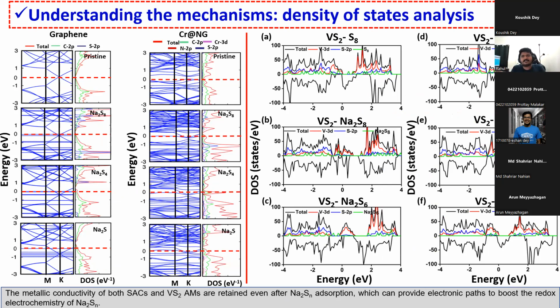Now we have done the density of states analysis to check how the conductivity changed before adsorption and after the polysulfide adsorption. Now we all know that graphene is a zero band gap semiconductor, right? You can see here clearly it's a zero band gap semiconductor, but when we put the polysulfide, you can see slight states at the Fermi level.